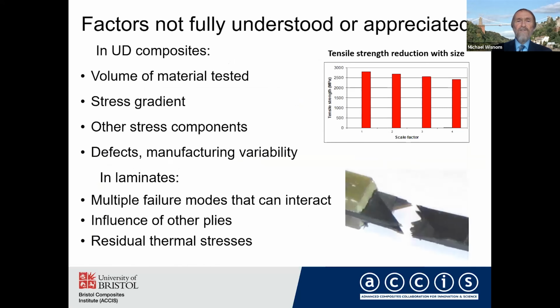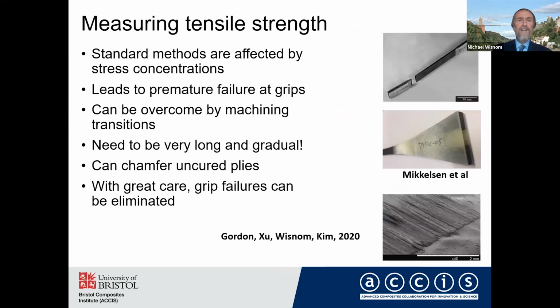Moving on then to factors which are not fully understood or appreciated. In unidirectional composites, volume of material tested is very important. The stress gradient can be important. And then there's also the effect of other stress components, defects, manufacturing variability. And then in laminates, you've got the issues because there are multiple failure modes that can interact. You've got the influence of other plies, and you've also got residual thermal stresses. So I'm going to look at a few of these factors and start off by talking about tension.